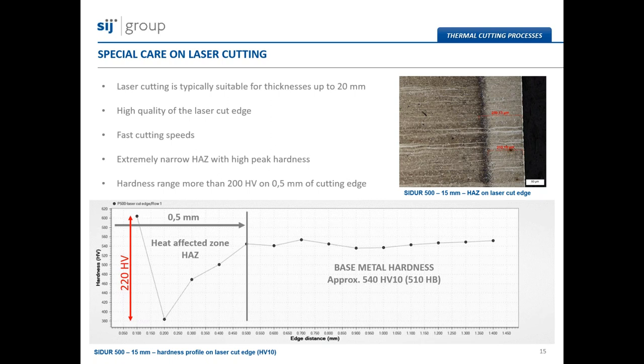Among all the other thermal cutting processes, laser cutting has the highest hardness peaks or ranges in this narrow heat-affected zone. So, when cutting high carbon equivalent value grades, like SIDUR 500, for example, we get microstructural changes in the heat-affected zone as shown on this figure. We have the white region in the microstructure, and this region is the quenched region. We have microstructural and mechanical changes there, and they appear only 0.5 millimeter away from the cutting edge.